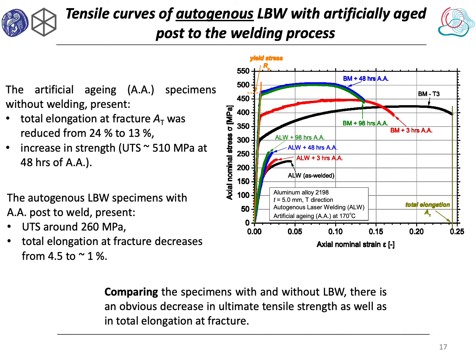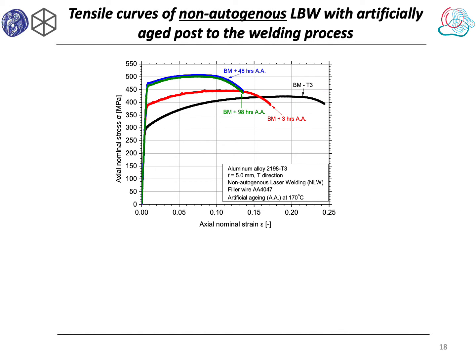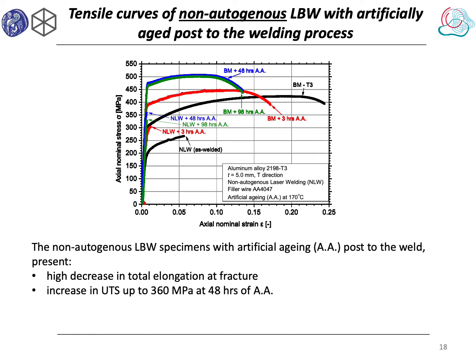Comparing the specimens with and without laser beam welding, there is an obvious decrease in ultimate tensile strength as well as in total elongation at fracture. Non-autogenous welds, with increasing aging time post to the weld, present a higher decrease in ductility and an increase of ultimate tensile strength up to 48 hours and peak aging condition.